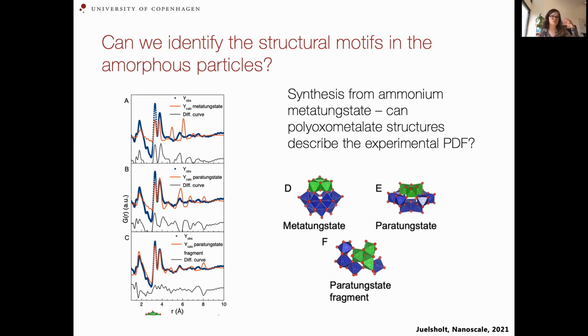And what we did here was to, again, like we said before, test a lot of different structures and see how it fits. But we found that none of the known crystalline structures could describe the structure of these amorphous nanoparticles. So instead, what we did was consider what other tungsten oxide structures we know. As briefly mentioned, when you dissolve tungsten oxides in aqueous solutions at different pH values, you can stabilize different polyoxometalates. So these kinds of ions here, or structures, which are large ions, which can be stabilized in different coordinations. And the synthesis was done from a solution of ammonium metatungstate, where metatungstate is shown here.